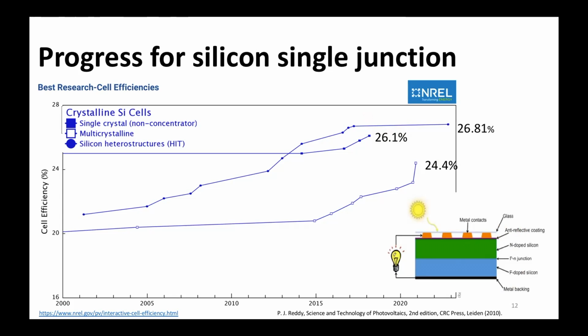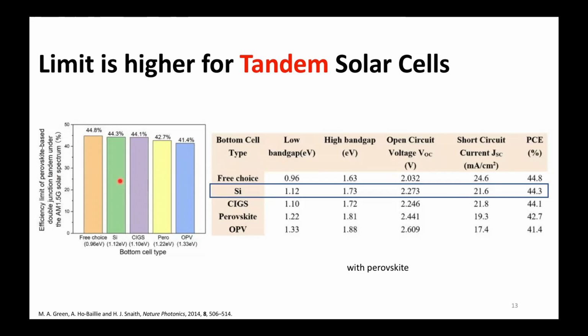Perovskites are a direct band gap semiconductor, so you don't need to do the trick with this doping. You can combine any types of materials. If you can choose all the properties, you can get up to 45%. Silicon perovskite, the limit is 44.3, and if you use organic materials, the limit is slightly lower. But for the combination of silicon with perovskite, this is the ideal band gap of silicon perovskite. And in principle, if you go to this limit, you can get 2.3 volts and about 21.6 milliamps. So then you get the theoretical maximum efficiency.